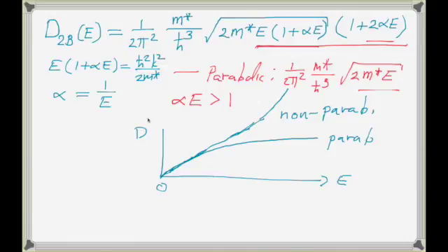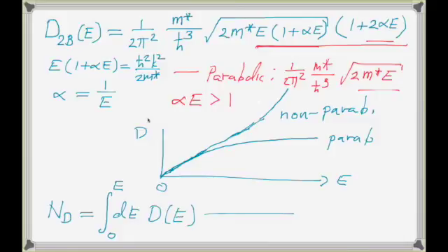And so as I said, usually the doping is given by the experimentalist. And in a simple model, you say the doping is equal to, say, the electron density. And the electron density would then be given by an expression like this, where you integrate the density of states times the Fermi factor, which is this exponentially decaying factor as energy increases. Doing this integral, you need to get the Fermi energy